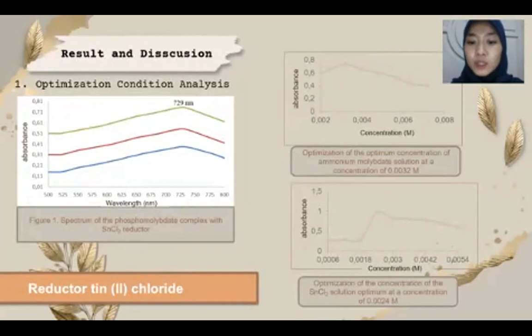Next, optimization of the concentration of the tin(II) chloride solution is optimum at a concentration of 0.0024 molar. If the concentration exceeds 0.004 molar, the absorption will decrease because a further reaction will occur, namely a decrease in intensity because Sn2+ turns into Sn4+.